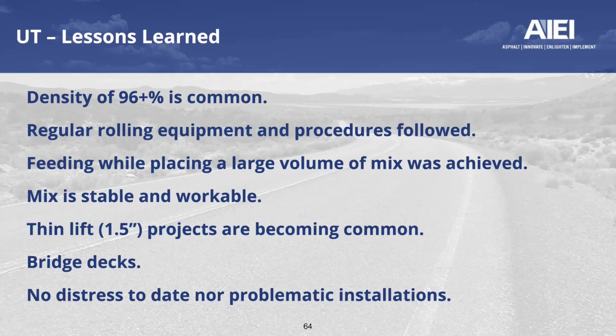It should be mentioned that there is a longitudinal joint density requirement in Utah as well. 94% is that requirement. Lift thicknesses of 2 inches plus are held to that level. There has been some struggles on a few projects on the 2-inch thicknesses of achieving that 94% density. It is my understanding that the contractors have, of their own volition, chosen to cut back those, much like you might see on an airport project. And with the cutback of that material, they're finding the 94% density tends to be no longer problematic. To date, we haven't seen any project failures. We haven't seen any notable distresses at any of the installations around the state.